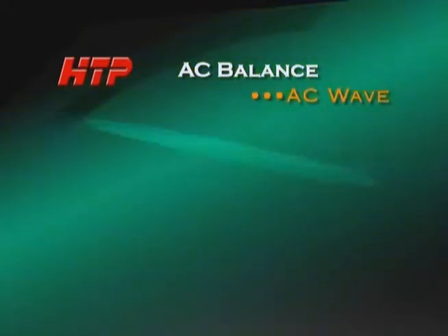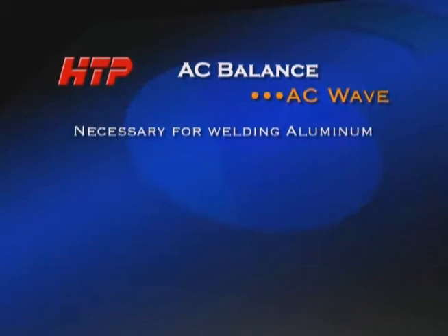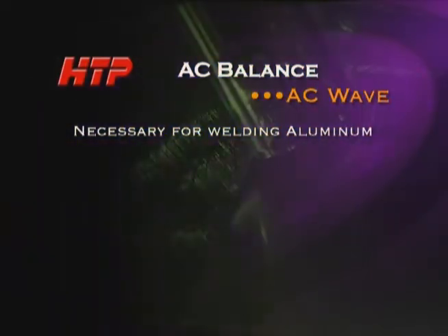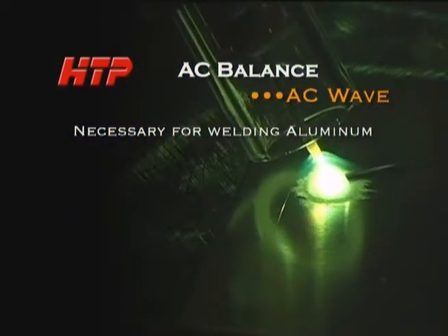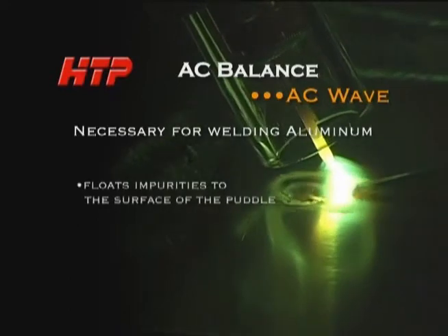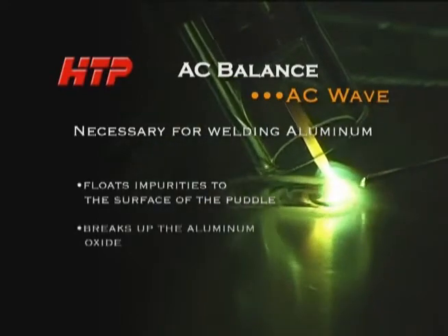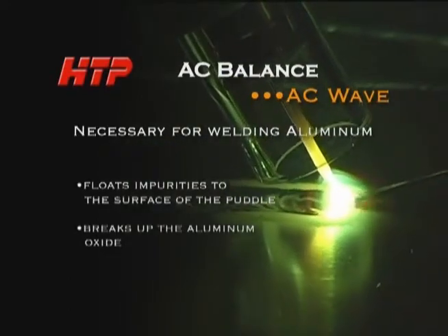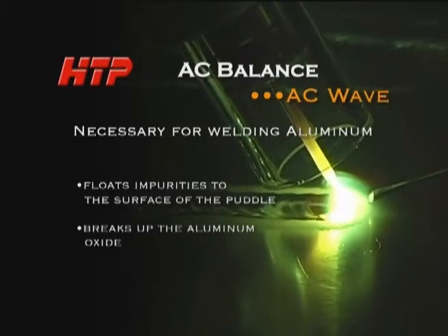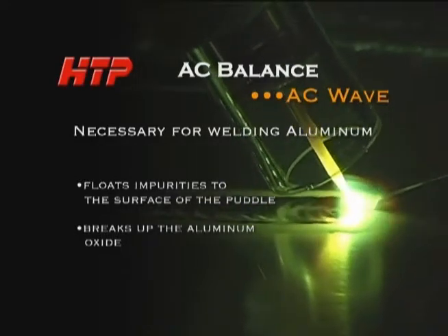An AC wave is necessary for welding aluminum because when the electrons are flowing from the workpiece to the torch, it helps float impurities to the surface of the puddle and also breaks up the aluminum oxide which forms on the surface of all aluminum which is exposed to the atmosphere.